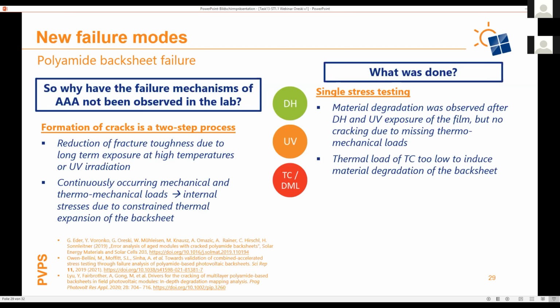And the problem was, with all these tests, you have either just reduction of fracture toughness, but no mechanical impact and no driving crack propagating force, or you just have the mechanical loads, but no material damage that you need in order for the crack to be initiated and grow. So you couldn't catch it.